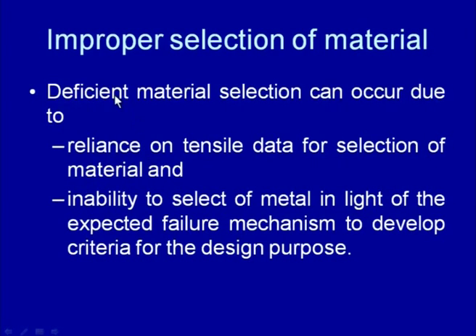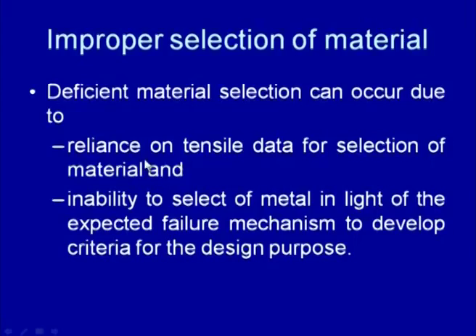But sometimes, due to the inability to select the material, deficiency in the material selection can occur due to the reliance on tensile data. Many times we find that for the kind of material which is available or which is a potential material, we do not have the desired properties, for example creep resistance or the ductile to brittle transition temperature or the fatigue resistance or the impact resistance. The properties of the particular material to be selected are not available in respect of the design criteria. So most of the time we rely on the tensile data related with the material for its selection, and this kind of reliance on the tensile data is found insufficient, especially for the successful performance